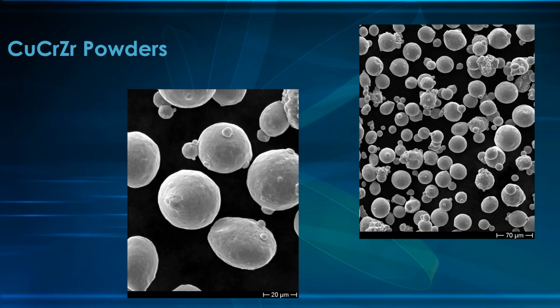In this figure, you can see the two SEM micrographs showing the powder morphology. So as you can see, we have spherical particles. Their size is below 45 micrometers, but if you observe the micrographs in the figure, you can see also that those powders are characterized by the presence of a large number of satellites. The presence of those satellites can be explained considering that those powders are recycled during the printing process.